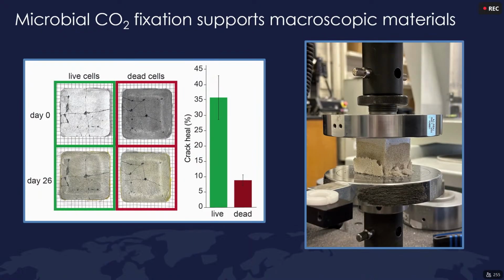And so what we all actually care about is how does this work with cement? This was actually a project for a group of high school students in my lab last summer. They mixed in different dry weights of microbes directly into cement mix. Those pictures on the left are 10 centimeter by 10 centimeter pucks. They then took a hammer and a nail to them. So that hole in the middle is from a nail. And if we just kept them in a humid environment, after a month, we got about 35 to 40% crack healing. And you can see that if you look from day 0 to day 26, the crack is filling in the middle from the bottom up.